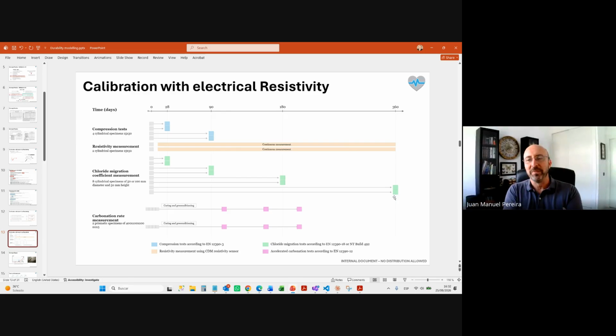because in 2 years maybe the building is finished. So our approach here is to take the resistivity sensors, these are our sensors, and when you do any testing plan, you just cast 2 additional ones for each concrete. So you have test specimens for strength and for chloride migration and for carbonation, whatever. You cast 2 more, and these give you continuous measurements, so you can keep reading up to any age. These readings will correlate to the strength, to the chloride migration, to the carbonation, to anything you measure. Just by adding 2 additional test specimens and leaving them there in a corner, in a tank, reading, reading, reading. You don't need to interact with them. It's just continuous.